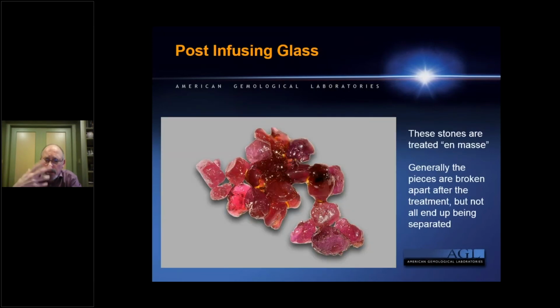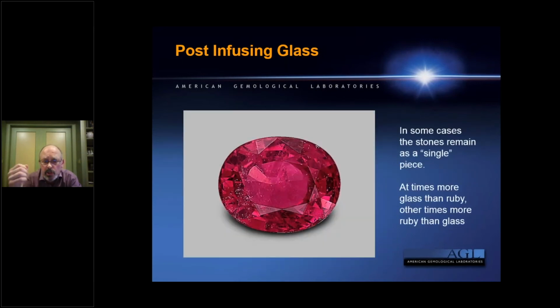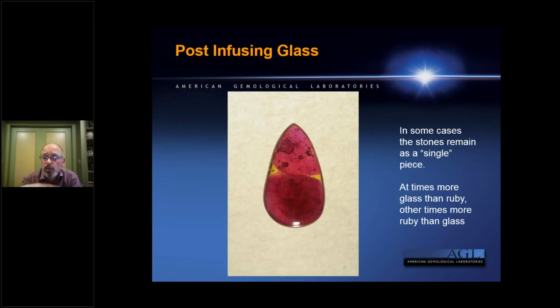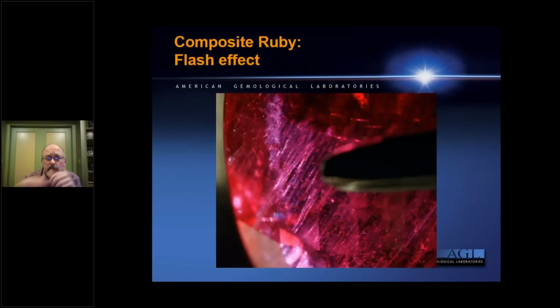They're treated en masse then in a high lead content glass. You can kind of see here. Generally, these stones are single pieces, so a single piece of rough will produce a single cut stone. However, because they're treated in such mass, you get masses of this corundum and high lead content glass at the end of it, and they'll quickly polish and fashion stones. Sometimes you actually have discontinuous pieces of corundum which are held together by the high lead content glass. Sometimes you have more glass than ruby, sometimes you have more ruby than glass, but it's always an essential component, both of these things.